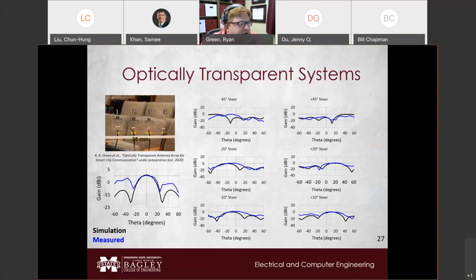We also found that you could possibly counter this low efficiency and low gain with a transparent array. Here we have a 4x1 antenna array operating at 5.8 gigahertz, and we noticed that the gain went from about -3 to approximately a positive 0.5, which again is a great increase in gain. The added benefit of having that phased array is that we can now beam steer, which, if you're not familiar with that term, ultimately just means that we can change the direction the antenna is broadcasting without physically moving the antenna, just by changing what phase the signal coming out of each antenna is set to.